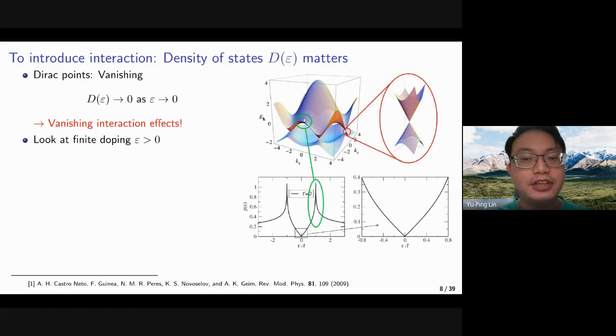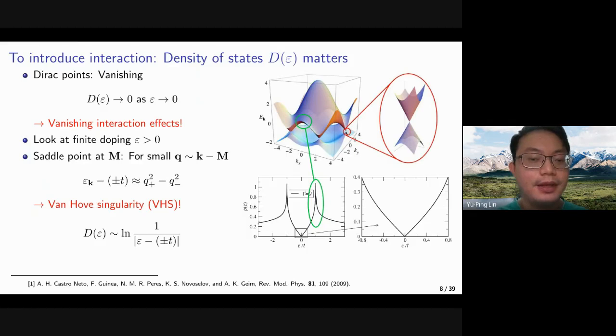So we should look at a finite doping where we could have a finite density of states. And a particularly interesting point are the saddle point at M, where if we have a small momentum deviation, then the energy deviation from the saddle point will be q_x squared minus q_y squared, where you can see that along one direction you have a negative curvature, and along another direction we have a positive curvature. So this kind of saddle point defines a Van Hove singularity in the density of states. That is, it will become logarithmically divergent as we approach the saddle point energy. And you can see from the density of states here that there is indeed a log divergence.